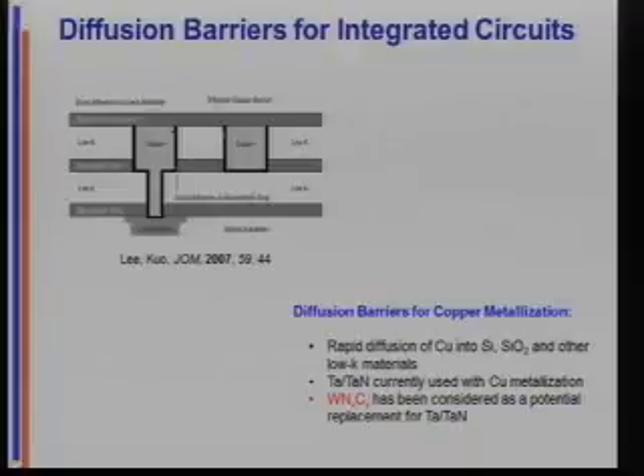And you see everywhere there's copper in this cartoon, there is a black line drawn. And that black line is diffusion barrier material. That's a thin layer of something that prevents the copper from migrating throughout the chip and shorting it out. Okay? And so at the time that we got into this, the industry was just making a transition from aluminum metallization here to copper metallized chips.